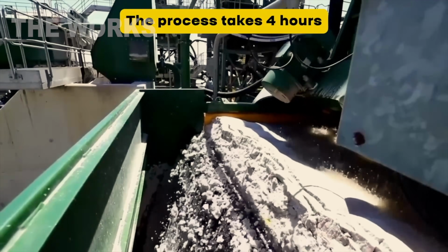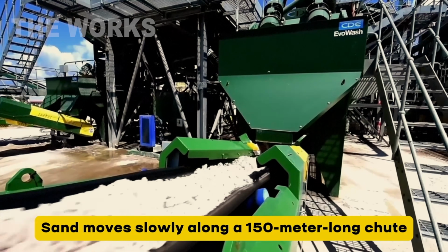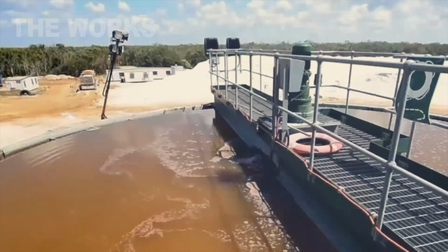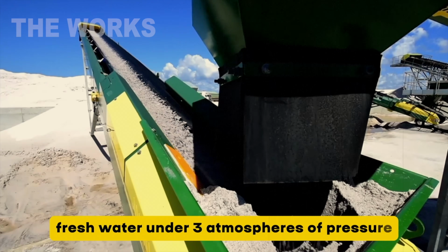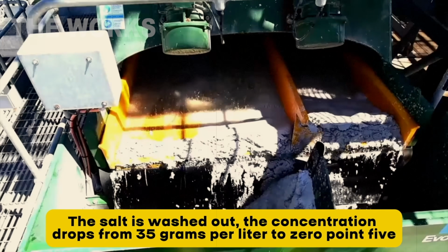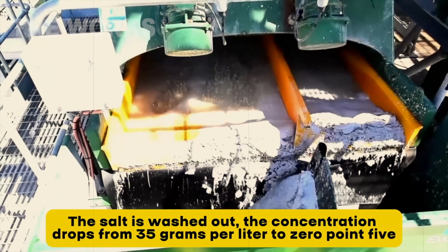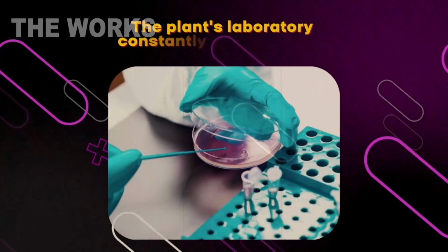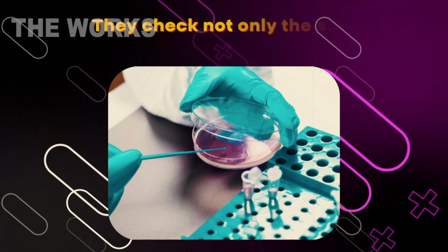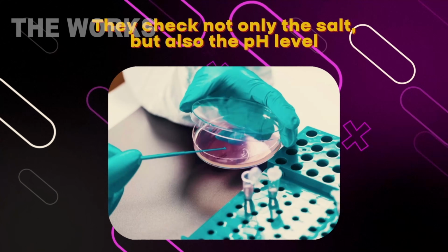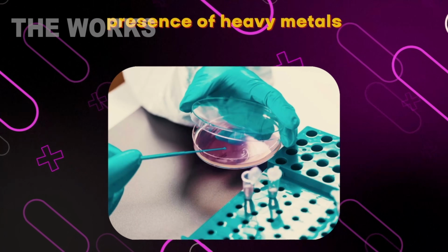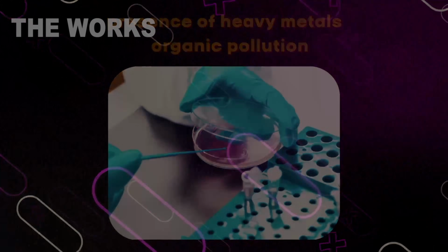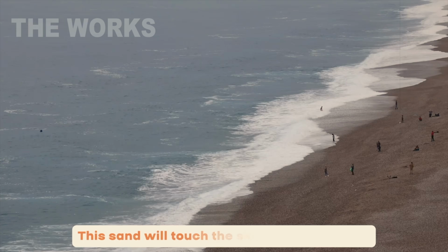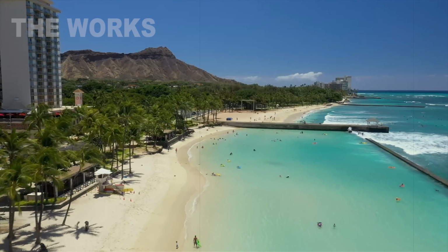The sand slowly moves through a trough about 500 feet long, while pressurized fresh water, at 3 atmospheres, pours down from above. The salt washes out, concentration drops from 35 grams per liter to 0.5. The plant's lab constantly takes samples. They're not just checking salt, but pH levels, heavy metals, organic contaminants. The standards are strict. This sand is going to touch the skin of thousands of tourists. Kids will be crawling on it. One mistake and the beach's reputation collapses.